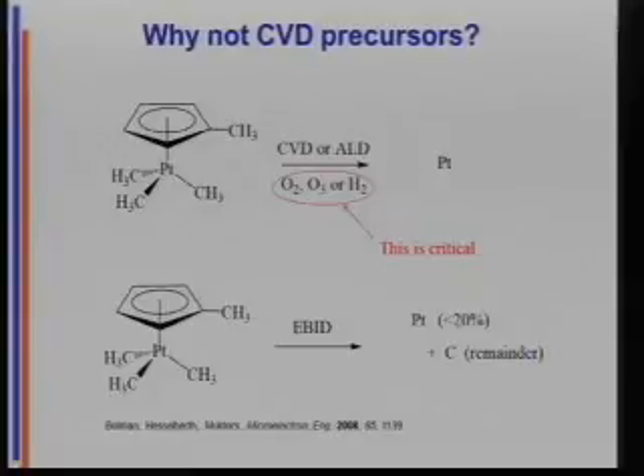In fact, what happens on this compound is you can knock off one methyl under EBID conditions, and the rest of the methyls are all incorporated into the deposit. And so what they try to do, it's called post-deposition processing, where they basically set the deposit on fire, trying to burn the carbon out. And then you've lost your exquisite 3D control of the patterning because, well, you get it.